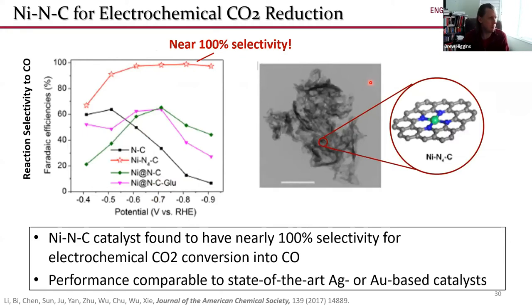Going towards optimizing this, choosing one's metals wisely, the field really moved towards the identification of nickel nitrogen carbon catalysts as being able to achieve nearly 100% selectivity for the conversion of CO2 into carbon monoxide. When we're talking about selectivity, 100% sounds pretty good, because that means every single molecule of CO2 that's being converted is being converted into carbon monoxide, which in this case is the most desirable product. So that was really exciting. These nickel nitrogen carbon catalysts, with relatively low cost preparation and relatively low cost materials going into them, had very good activity and very good selectivity for producing carbon monoxide. This was activity comparable to state-of-the-art silver or gold-based catalysts, but at a fraction of the price.